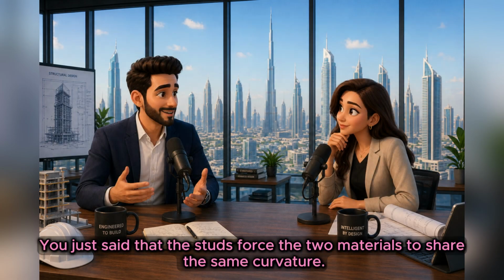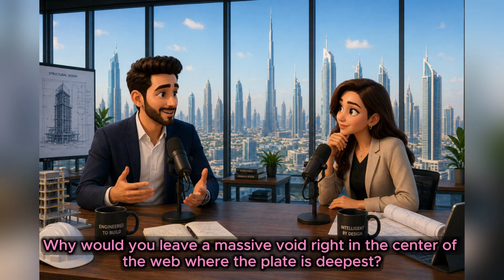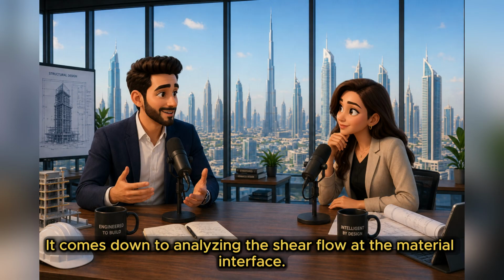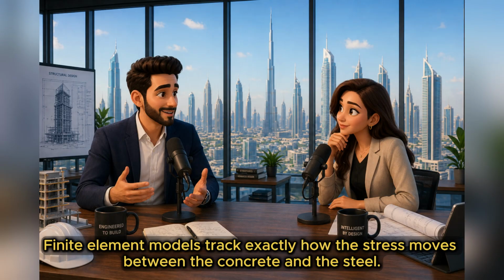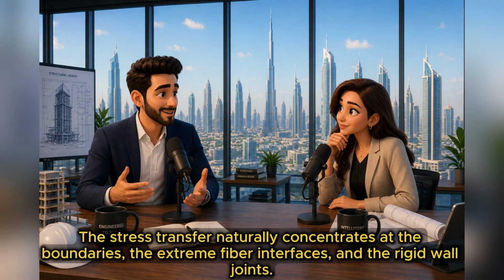0 shear studs. Wait, hold on. You just said that the studs force the 2 materials to share the same curvature. Why would you leave a massive void right in the center of the web where the plate is deepest? It comes down to analyzing the shear flow at the material interface. Finite element models track exactly how the stress moves between the concrete and the steel. The stress transfer naturally concentrates at the boundaries, the extreme fiber interfaces, and the rigid wall joints.